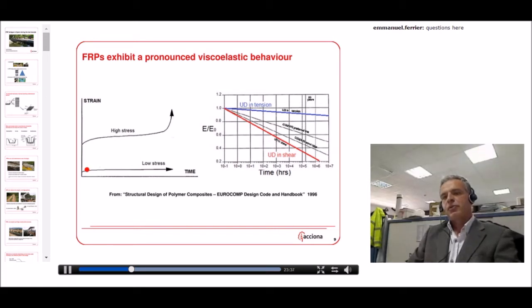And the second step, you have to have sufficiently low stress induced by sustained load. The second step, you should take into account the apparent reduction in Young's modulus due to the creep. Here you have an example. On the ordinate, you have the ratio between the apparent Young's modulus and the initial modulus, and here the time. And you see how different the behavior is of a unidirectional laminate in tension and a unidirectional laminate in shear.